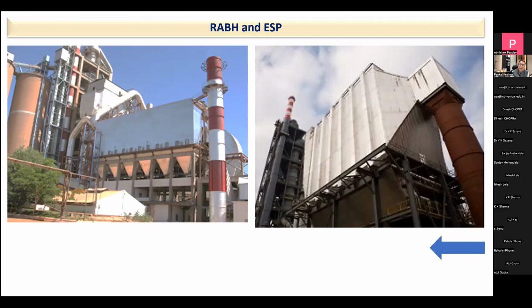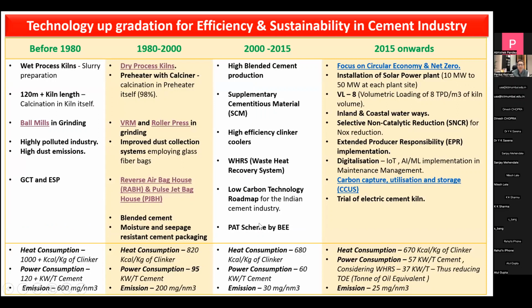But now, if we look at the current statistics, the fuel consumption has gone down from 1,000 kilocalorie to 820 kilocalories and power to 95 kilowatt. And emission has gone down from 600 to 200. This is prior to 2000. Now, after 2000, things have still further improved, and heat consumption has gone down to 680 kilocalories, and power is also reduced to 60 kilowatt.